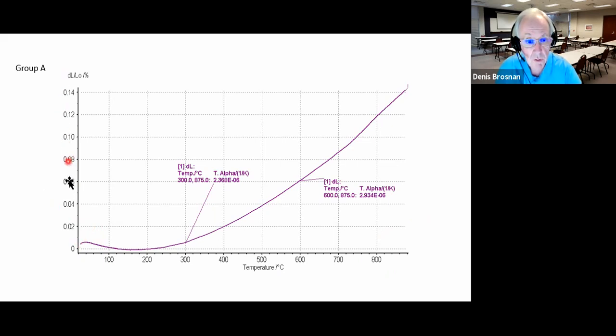Thermal expansion, delta L over L0 expressed as a percent. Change in length per unit length expressed as a percent versus temperature on heating. The fired cordierite went negative. So obviously we were able to get a little bit of clay alignment. The thermal expansion coefficient was 2.35 in the low temperature region of room temperature up to about 300 degrees C, up to 600 degrees C, it was 2.9. So we were down around 2 in thermal expansion coefficient. Not as good as commercial cordierite, but pretty good.